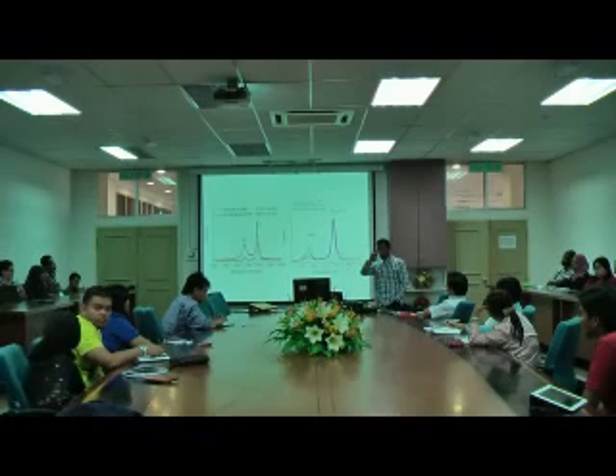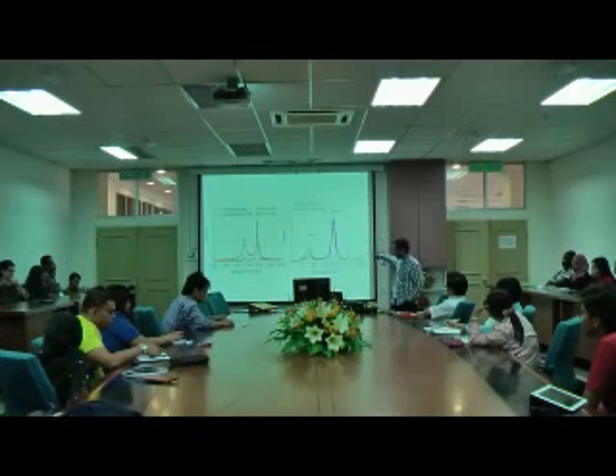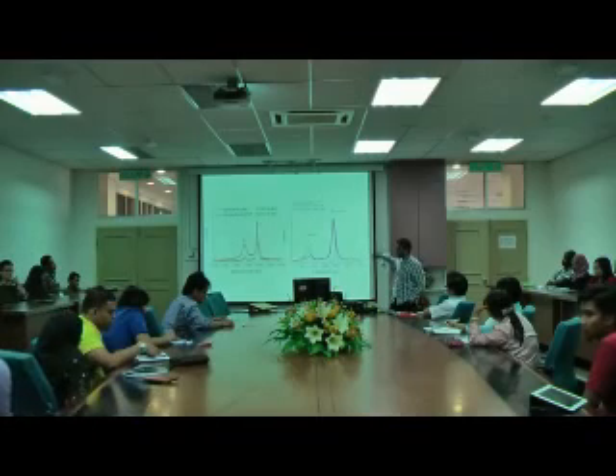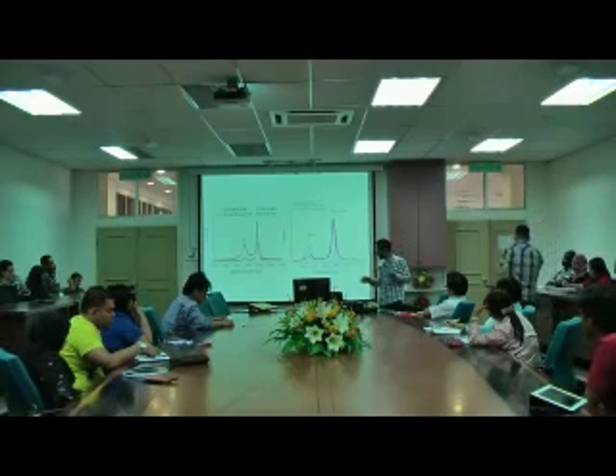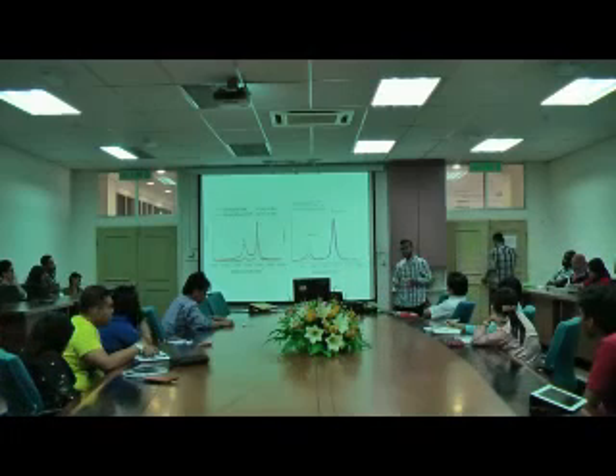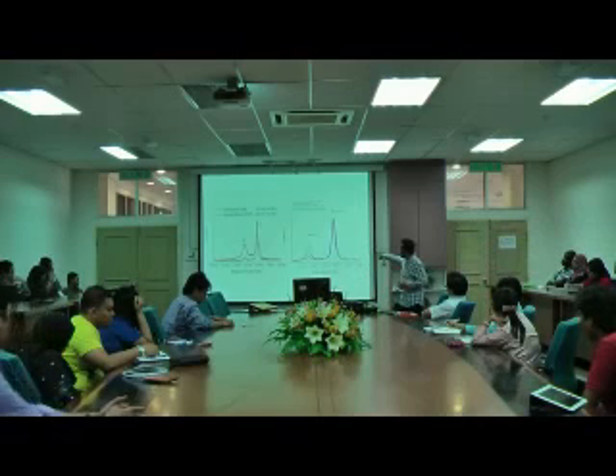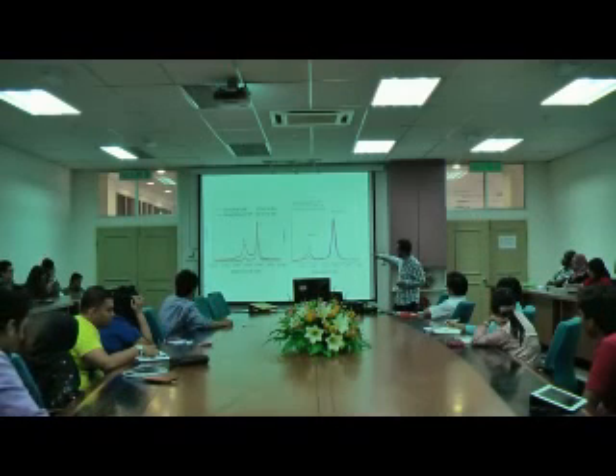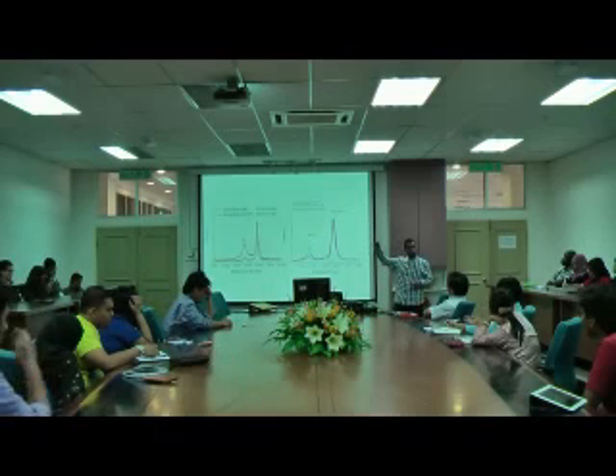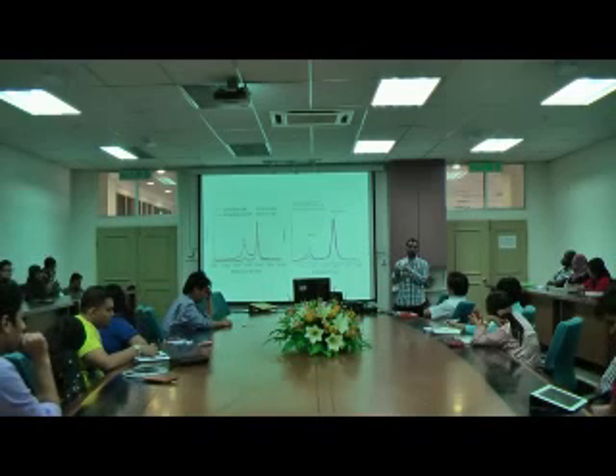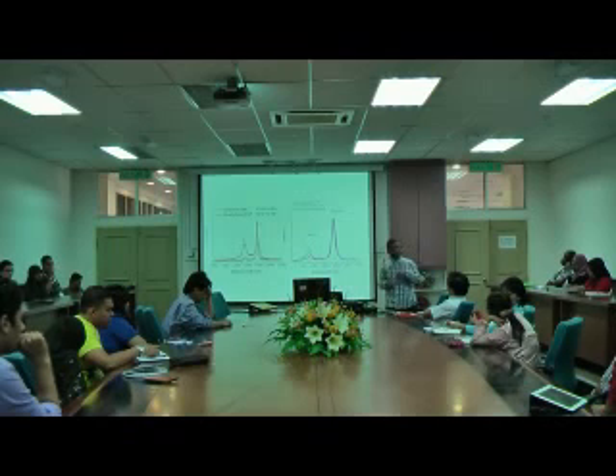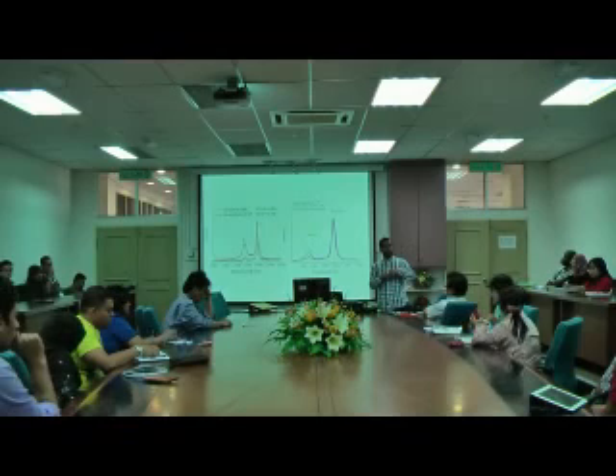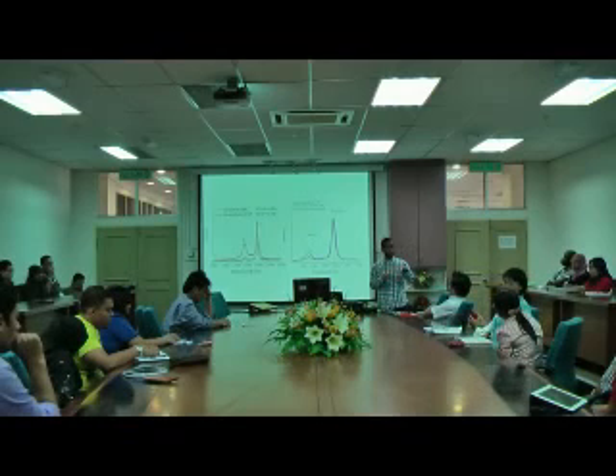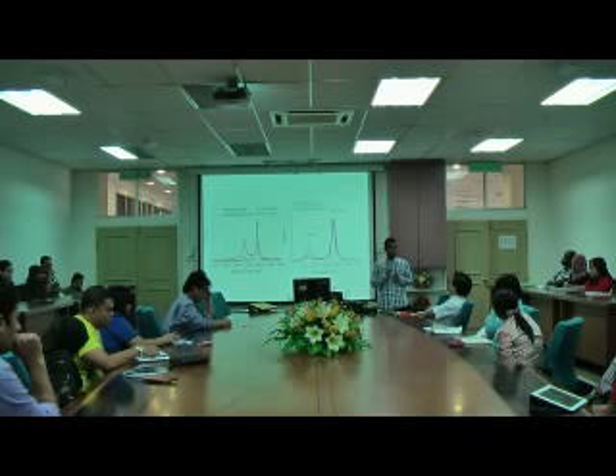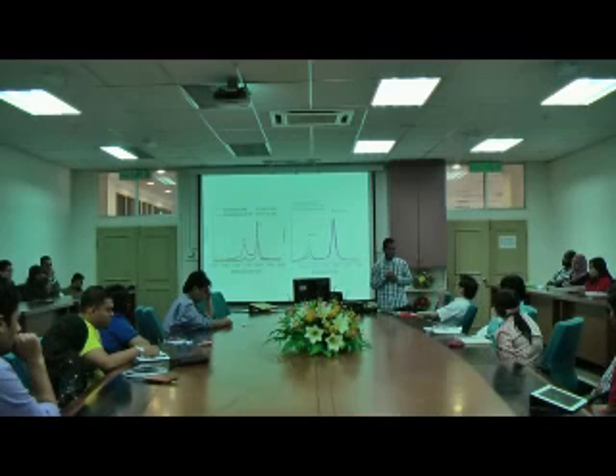With graphite or carbon, you have these two signature peaks. That refers to the graphitic band, the phonon vibration in graphite, and the defect band. So if you introduce some amount of defects, then the defect band increases. So this is like the control. Does that answer your question? No. I don't have numbers like how many defects I produce. It's sort of a relative quantity. So the ID ratio is basically that.